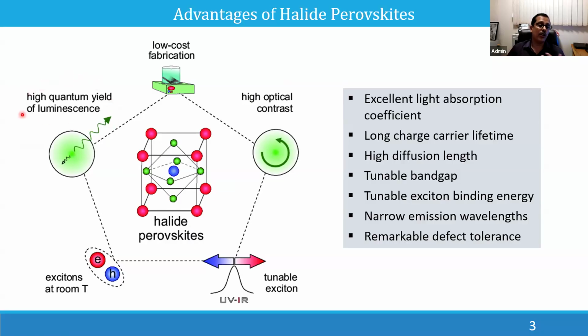Quantum yield is the ratio of the energy you gave to the energy in photons you emitted. So if it is very close to 1, it is the best. And if it is below 50% or 40%, it is not suitable for many light emitting applications. Normally this perovskite material shows very high quantum yield, not only the luminescence quantum yield, but also the electroluminescent quantum yield. In most devices, it is electroluminescence, not photoluminescence. So in both cases, electro and photoluminescence, it shows very good efficiency. It is very close to 100% efficiency in many cases. So that is one reason.